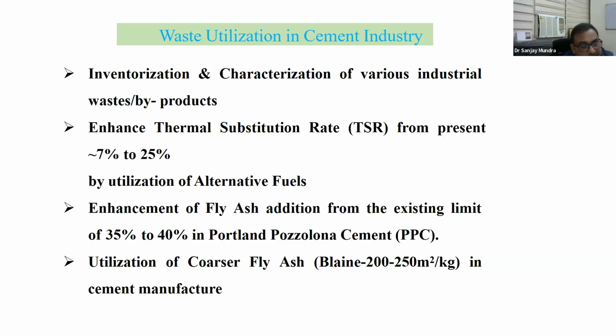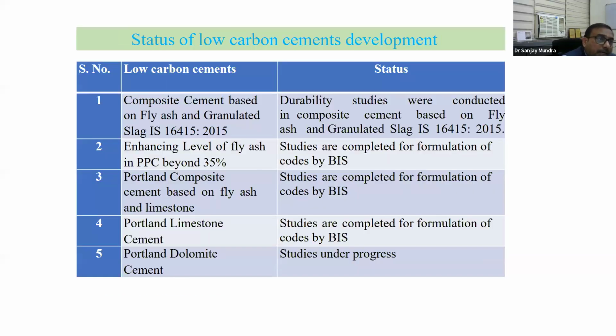As you know, the fly ash earlier we were using with a 300 meters square per kg, but now we are targeting that coarser fly ash is also good for manufacturing purpose. So we are having the target for Blaine of 200 to 250 meters square per kg. This is the status of low carbon cement development. Composite cement based on fly ash and granulated slag. The IS code has already been published in 2015 as 16415. Then durability studies were conducted in composite cement based on fly ash and granulated slag, and it is promising.